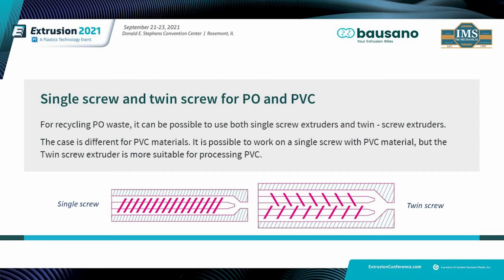For recycling PO waste, it can be possible to use a single screw extruder or twin screw extruders. It depends on the original waste and the specific project. When recycling PE in a single screw, the L over D, or the length over diameter, will need to be longer than in the normal single screw extruder. It is possible to process PVC on a single screw, but the twin screw extruder is much more directed towards that. One simple example is due to the PVC's rougher nature.